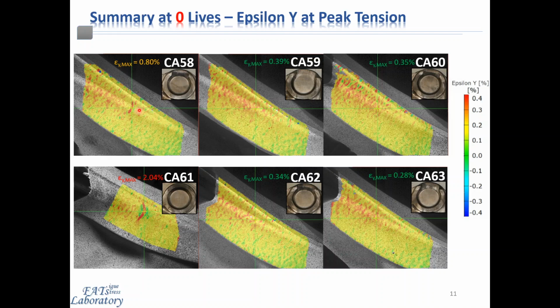In general, the strain field is not totally homogeneous, as this is a component level test with varying stress and strain gradients throughout this particular field that's being captured and measured. The slight inhomogeneities illustrating themselves here as red spots surrounded by a yellow matrix or surrounding yellow areas are due to the unique microstructure of magnesium and its hexagonal close packed crystal structure. The local texture in these regions is slightly varying, meaning certain grains may have preferentially strained to accommodate the loading, whereas adjacent grains behave with a higher strength and have a slightly different texture, which means they will behave with slightly less strain when observed using this digital image correlation technique.